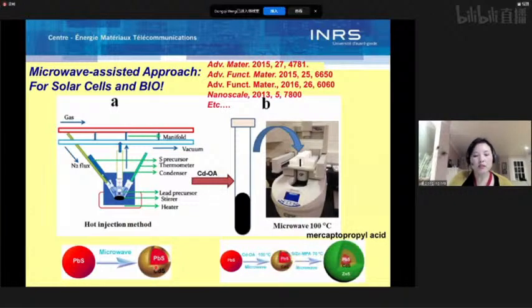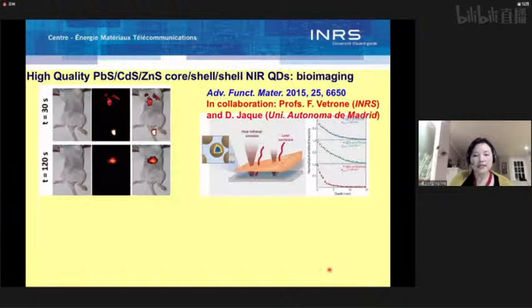To make quantum dots water-soluble or water-dispersible, we did another coating, zinc sulfide, on the surface by the microwave approach, and in the same process, we replace hydrophobic ligands with hydrophilic ligands, which allow us to transfer quantum dots into the water phase. So with this core-shell-shell approach, we get quantum dots which can be excited by near-infrared light, emit in the near-infrared, and also have high stability and high photoluminescence intensity.